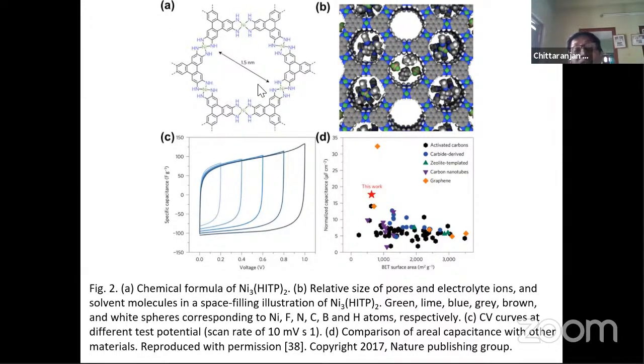In this cavity, when a charged species comes inside, its energy is much higher than that of the charge which is running through the bond over the metal organic hybrid system. I mean to say, when charge carries through nickel to organic group and so on, and the charge transportation from this organic molecule to this organic molecule through space are quite different. And when charge enters into this cavity, its energy is quite different. And that is interpreted in the capacitance property of the material.